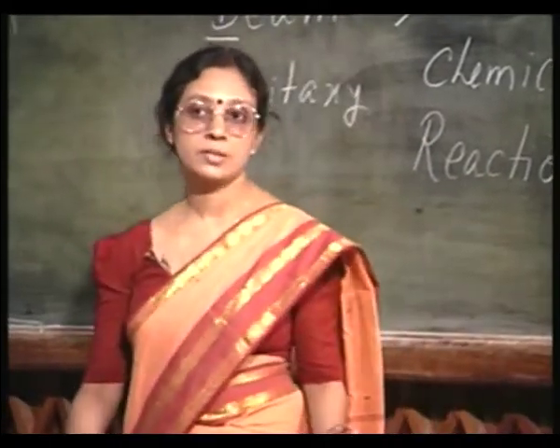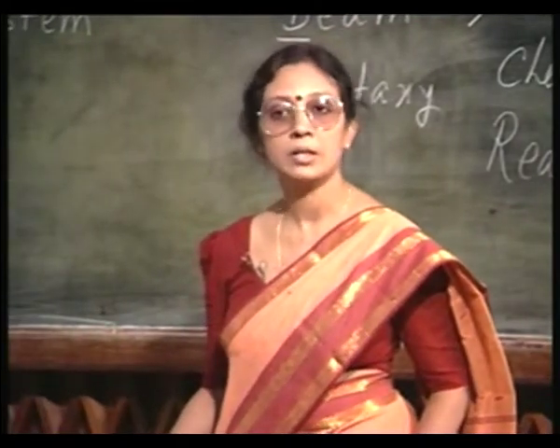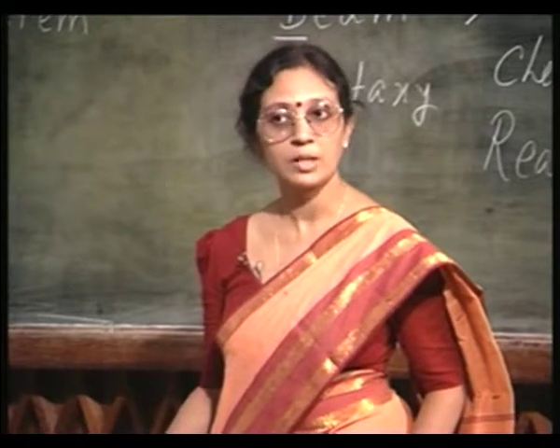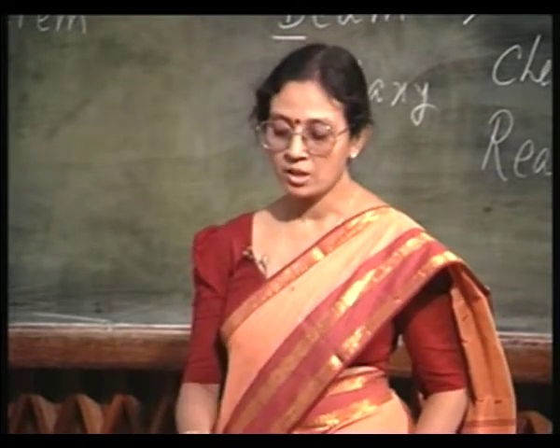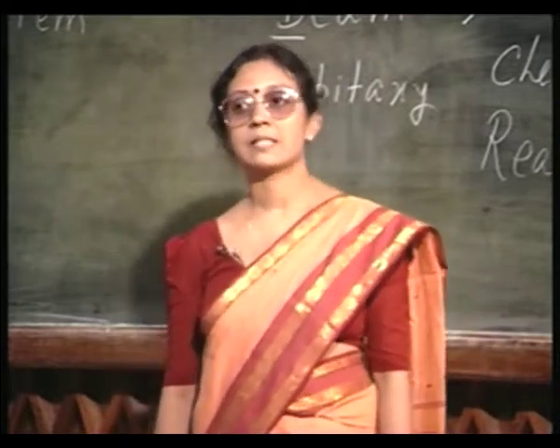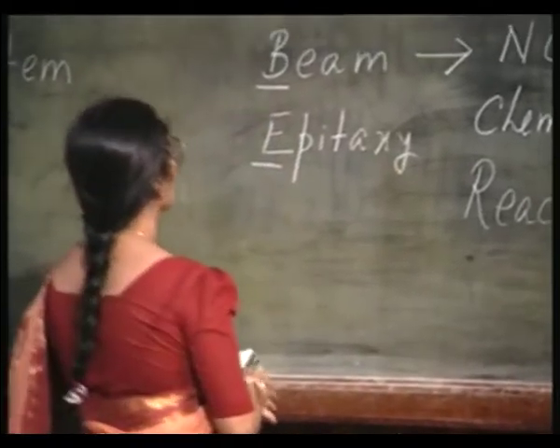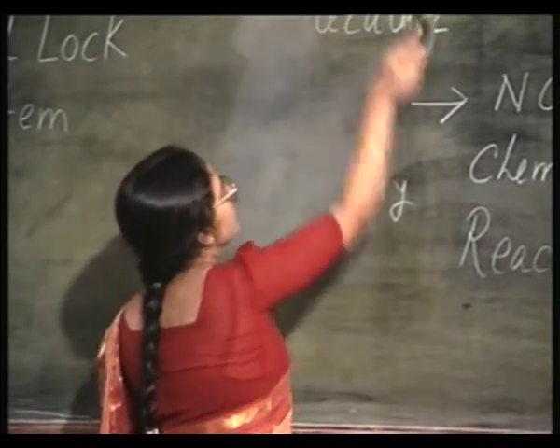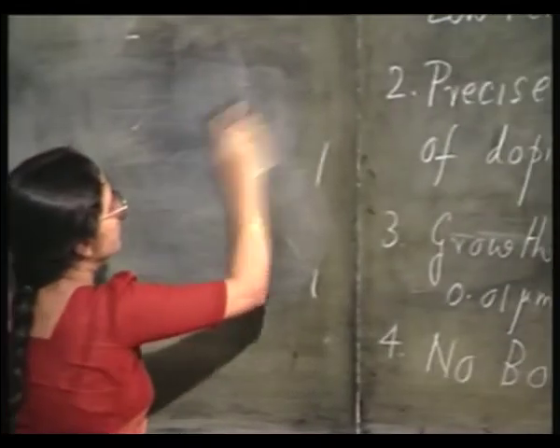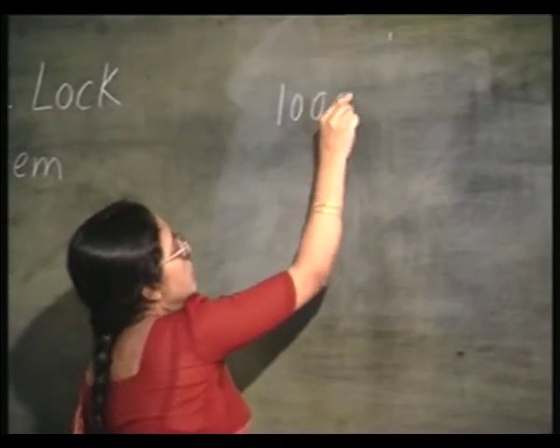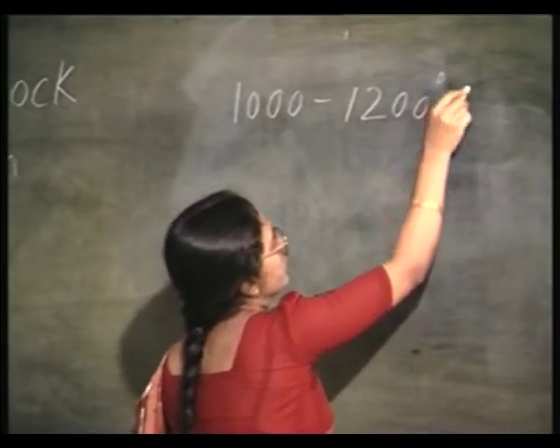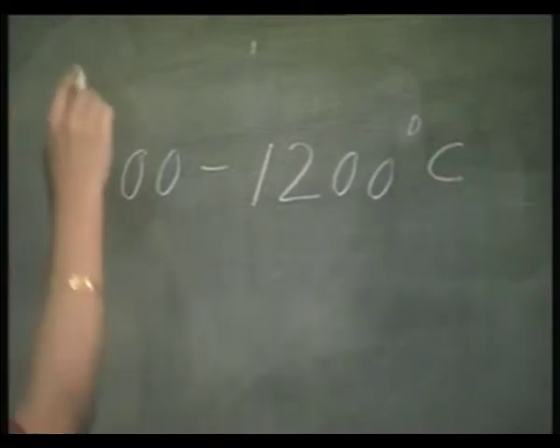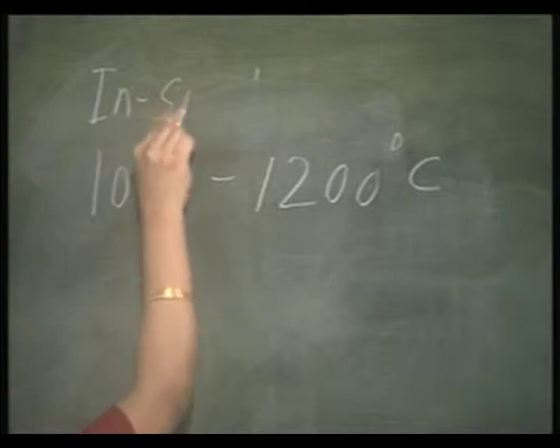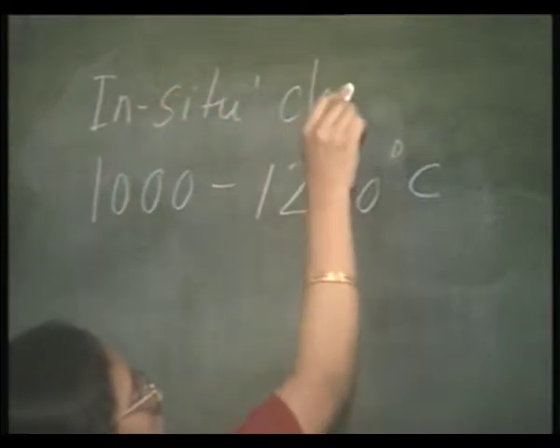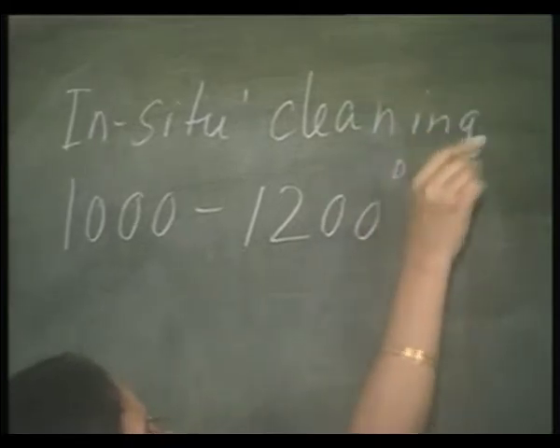Please understand, in the MBE system I usually have no provision for a chemical etching. So, what is done is you can either bake it at high temperature, that is 1000 to 1200 degree centigrade, bake it in vacuum in order to clean it in situ.